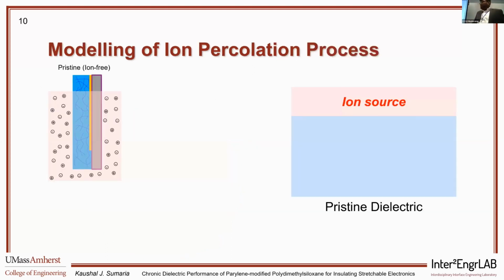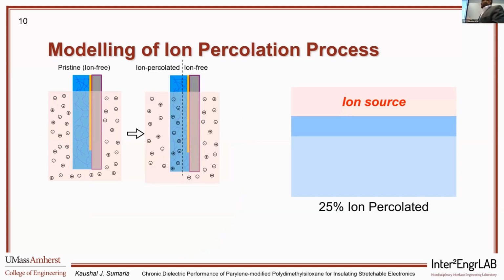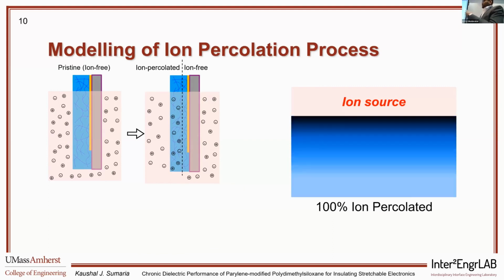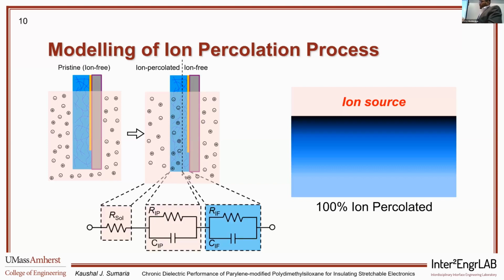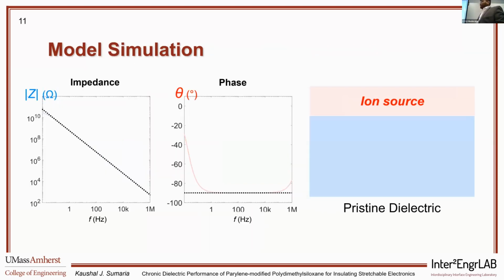So now, before we look at the results, let's see how ideal ion percolation or a diffusion process would look like. Initially, we have the dielectric that is completely free of any ions here. And then once it's subjected to an ion source, the ions will start percolating, and it will divide the dielectric into 2 parts. The one that is completely ion-free, closer to the gold electrode, and the one that is diffused with the ions closer to the solution. Based on this, our model considers these 2 parts, the thickness of which varies over time as the diffusion process progresses. So we simulate this in MATLAB.